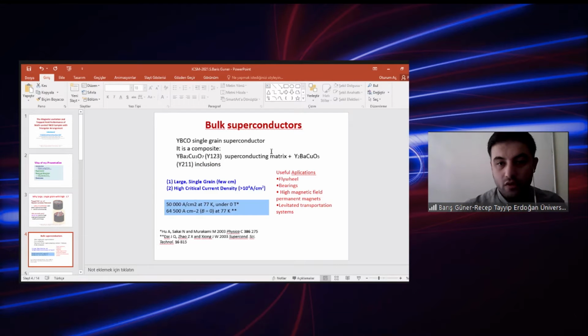For bulk superconductors, we generally study the YBCO single grain superconductor and gadolinium barium copper oxide single grain superconductor. YBCO is a composite, with a Y123 superconductive matrix and Y211 non-superconductive particles. The size of the superconductors can reach a few centimeters, and they have high critical current density. There are also many useful applications such as flywheel bearing systems, high magnetic field permanent magnets, and levitated transportation systems.